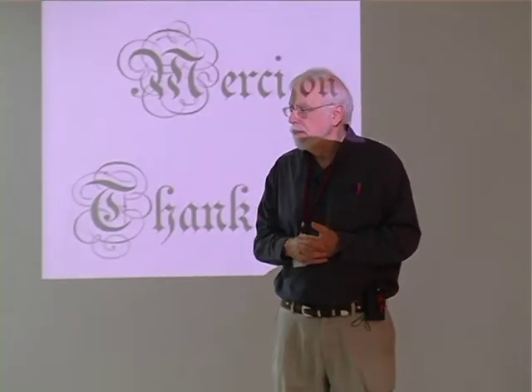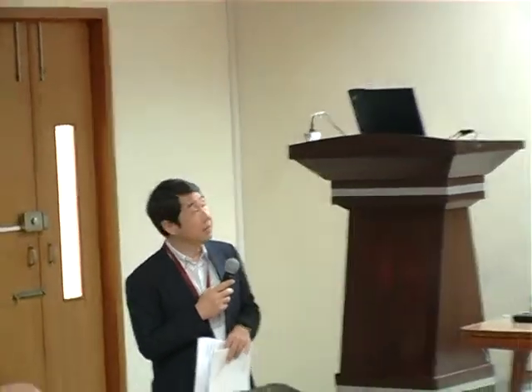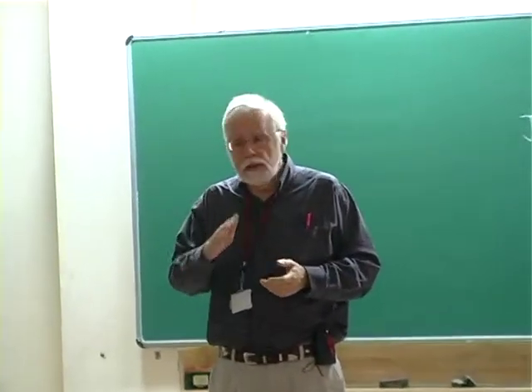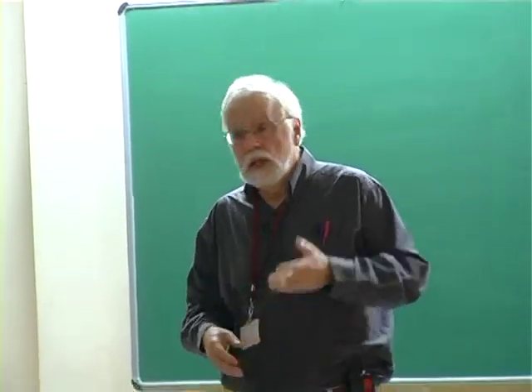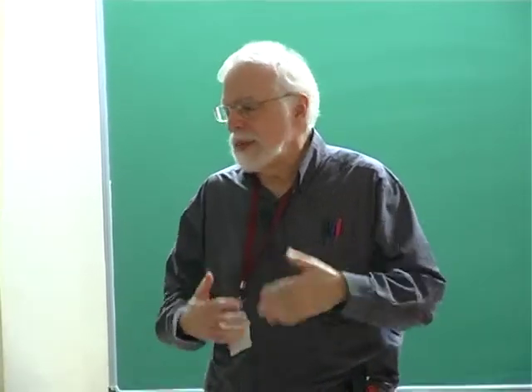Let me ask a quick question. You said electron-doped cuprates are weakly correlated. More weakly correlated, yes. The parameters are different. For example, U is smaller. And the electron-doped are simpler. I mean, there's only antiferromagnetism and d-wave superconductivity. And the pseudogap line you can explain just from antiferromagnetic fluctuations. There are predictions that the pseudogap appears when the antiferromagnetic correlation length becomes of the order of the thermal de Broglie wavelength, and it's observed experimentally. And there are predictions that z, the dynamical exponent, should be 1, and it's observed experimentally. So when antiferromagnetism and superconductivity get together, then all hell breaks loose, and it's very hard to treat. But otherwise, it seems relatively simple to explain.